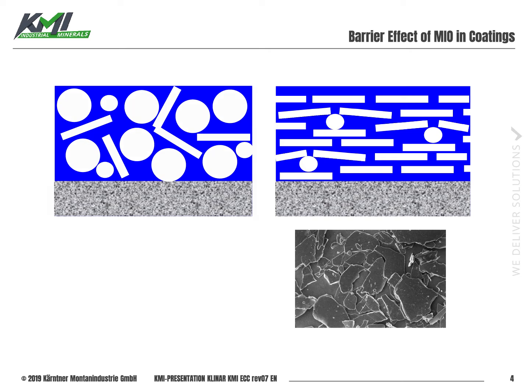In the examples here on the left hand side you see a picture where you have a mixture of granules and lamellar particles, and you can see it's not possible to get a good barrier layer or barrier effect in the left hand side example. On the right hand side you can see a product predominantly consisting of platelets, and it's in a good position to build up a very dense barrier layer to protect the substrate.